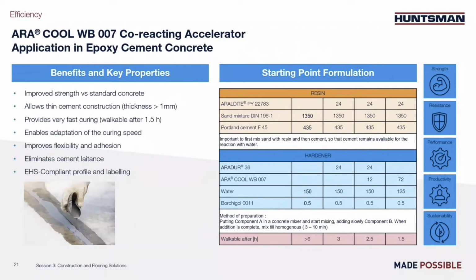Voilà. Here is another example of use of this new accelerator, and in this case with cement. So the principle is epoxy cement concrete, and basically cement needs water to react. So by using waterborne epoxy, we can introduce in the cement some organic epoxy thermoset, which brings some additional properties to cement, like strength. Here, the Aracool waterborne 007 also brings some acceleration to fasten the curing.